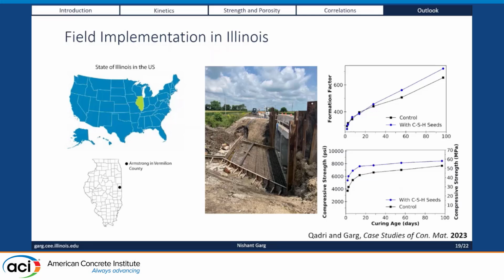And this allows them, if they want to open the pavement or the bridge deck early, or whatever they want to open early, right? To be very fair here, the strength gain is on the order of 15 to 20%, right? It's not going to be 50% or 80%, at least from these commercial systems. If you make it in the lab, you can definitely make it super doped. But on the commercial system, this is the order of strength that we're talking about. So people are also thinking you can reduce your cement content by 10% or so, and get that equivalent performance and get a different GWP and so on.